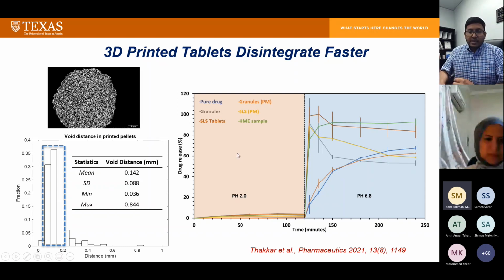As a result of that, and the single step manufacturing of amorphous solid dispersion, we found that our tablet showed much better release compared to the comparative formulation. So that was a really good indication of proving the concept that our Dose Plus can really be used for enhancing the physicochemical properties of poorly soluble, challenging molecules.